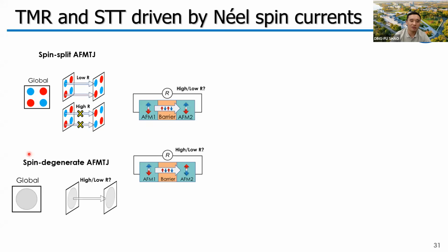This means we can never use antiferromagnets with spin degenerate film surfaces as an electrode in these tunnel junctions, because in this case it only supports the spin neutral conduction channels. So in parallel and anti-parallel states, the conduction channels will always match, and we cannot generate a difference of transmission.